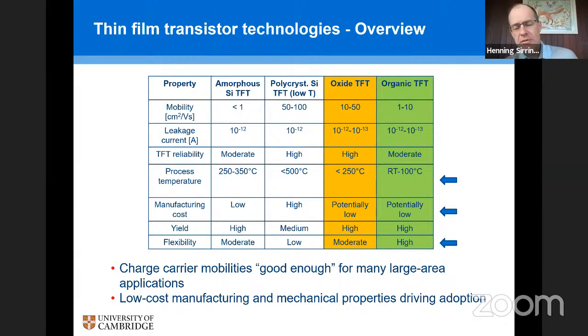But what the organics have going for them is the ease of processing. You can process them pretty much at room temperature or below 100 degrees C. That enables you to work on flexible substrates. And then, of course, also the mechanical properties. Some of these organic materials, at least when they are in polymeric form, are highly mechanically flexible, and that allows you then to integrate electronics in new form factors. And those properties are the ones which are driving the technological adoption.